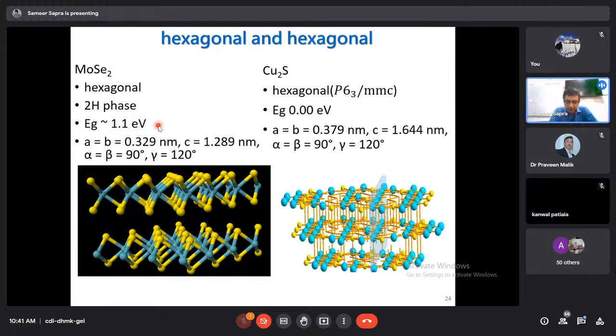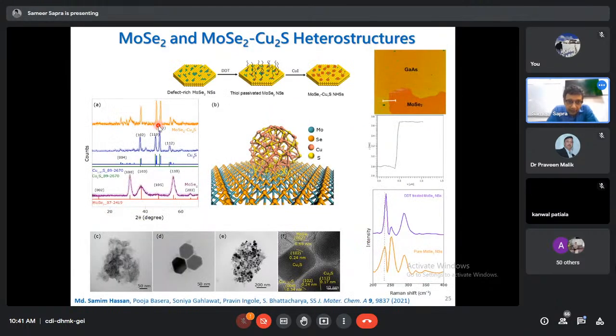So you couple these two materials, and how to couple them is something very innovative. You have all these defect-rich molybdenum selenide nanosheets. Okay, so these are defects. These are vacancies of selenium. So you put some dodecanethiol on top of it, and dodecanethiol has sulfur groups, okay, SH groups. Those can fulfill the selenium vacancies. They go and stick on top of these vacancies.